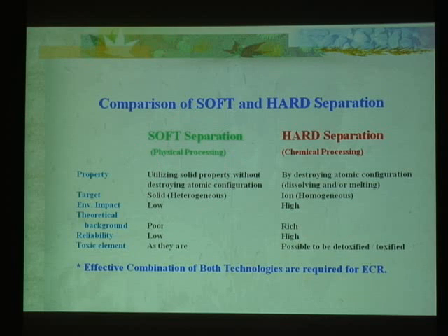And soft separation is just like a solid state separation. The property is utilizing solid property without destroying the atomic configuration. Theoretically, this kind of separation needs no energy, if we can separate statically. But hard separation, by dissolving or melting, of course destroys the atomic configuration and requires activation energy, theoretically.